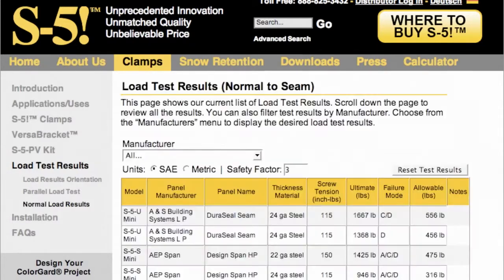The table is columnar with a clamp model on the far left, the name of the profile by alpha, its manufacturer alphabetically listed, the name that they call that profile, the gauge thickness of the panel, the screw tension at which the load test was run, then the ultimate failure load, the mode of failure, and in the last column on the right, the allowable load. You will also see the factor of safety in this window, and it can be reset by the user if desired. When relying on these tested values, be sure that the set screws are tensioned adequately. We will talk more about set screw tensioning a bit later.